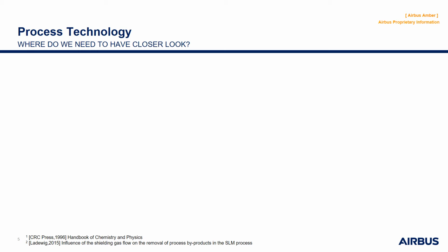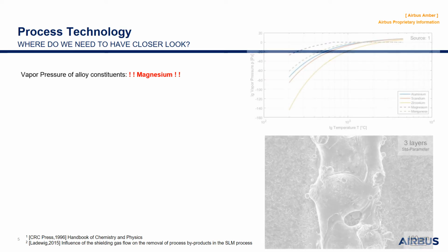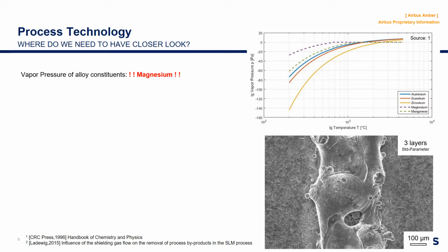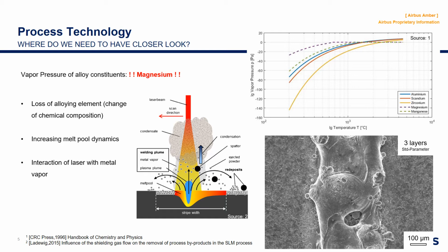If we now take a look at the impact of magnesium onto the process, we see magnesium has quite a high vapor pressure compared to aluminum. This has for sure different kinds of impacts. First of all, the chemistry of the alloy is different due to evaporation of this element with the high vapor pressure. Also, the vapor is interacting with the laser, and due to the increased magnesium content, the surface tension is decreased. So we increase the melt pool dynamics significantly. And all this is leading to a high probability of material inhomogeneity, as you can see on the right hand side. There are three single layers on top of each other, and already after these three layers we face a material inhomogeneity.